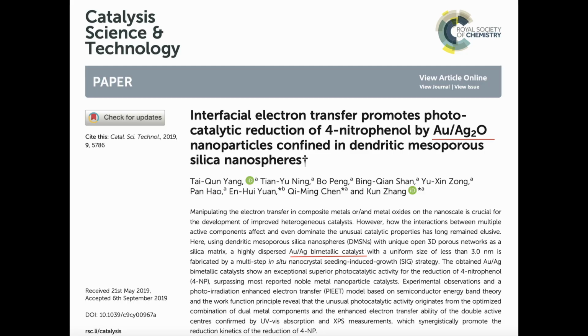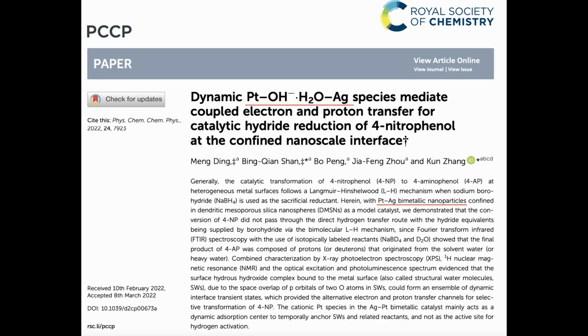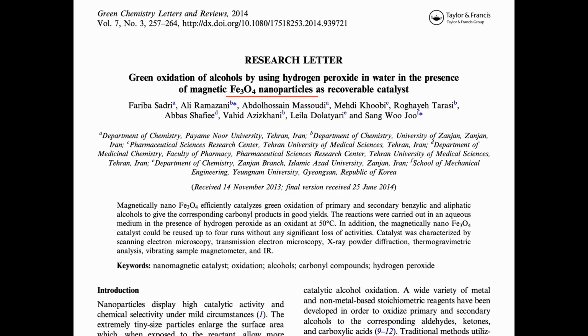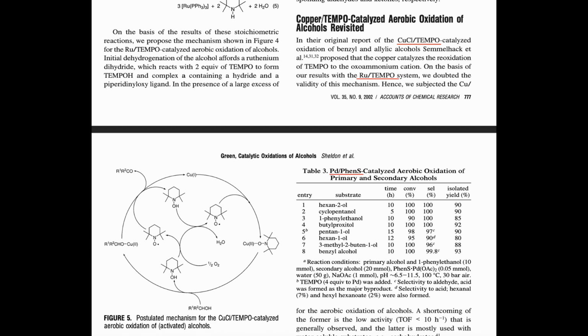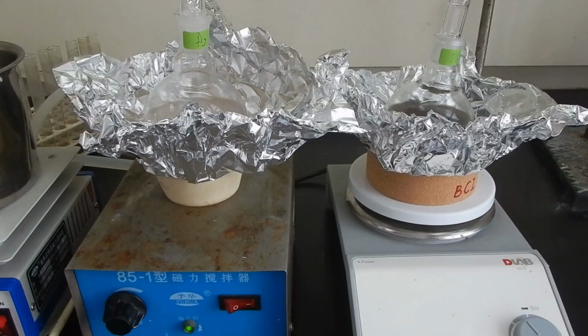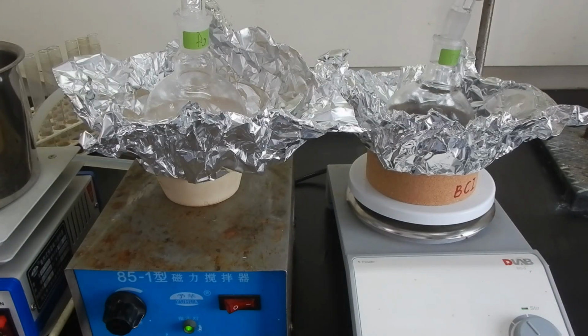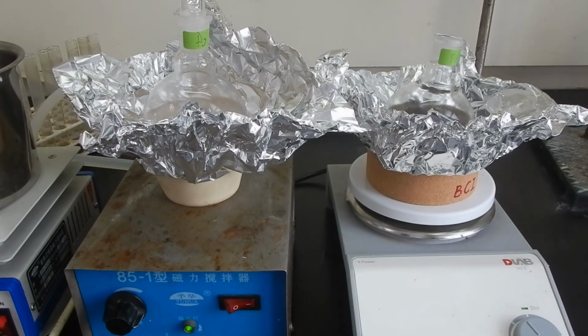My mentor's group worked with this DMSN material for quite a long time, and their experience says that transition metal nanoparticles work best with it. Fortunately, many transition metals like iron, copper, and silver catalyze alcohol oxidations quite well, so for now, things do look good. I decided to make 2 batches of catalyst, each containing silver and palladium respectively. These elements are the most promising candidates among noble metals, as gold and platinum didn't work well in a preliminary experiment, and I wonder which gives the best performance.